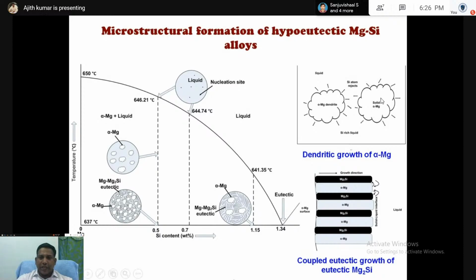So in the interdendritic region, this is the interdendritic region. During the growth, because the solubility of silicon in magnesium is very less, that is 0.02%, it will reject the silicon atoms out of the dendrite. So in the interdendritic region, the silicon phase is rich. When it reaches 637 degrees temperature, immediately the lamellar kind of eutectic will form. This is called eutectic structure.